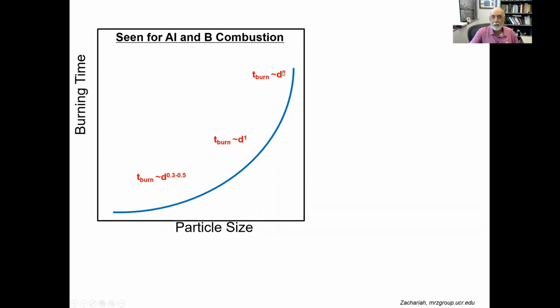You get the d squared burning law that some of you know from droplet burning. And then when particle sizes get smaller, there's a surface burning, and so you get a scaling with diameter. And then when you get to the nanoscale, things don't really look so good because the scaling with diameter falls dramatically. In other words, there isn't as much advantage to going to smaller particles if you have such a weak dependence on diameter. Now, why would you get this? Theory doesn't explain this.